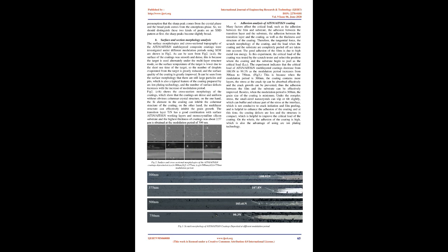The pitting of the AlTiN/AlTiSiN coating was carried out by an Anton Paar Tritech SA type pitting instrument, speed 500 rpm, time 600 s. The thickness of the coating can be obtained by observing the shape of the pits with a three-dimensional microscope. The hardness, H, and elastic modulus, E, of the AlTiN/AlTiSiN coatings were measured by the continuous stiffness method with a G300 nanoindentation instrument, and the H/E and H^3/E^2 values were calculated. The nanoindentation instrument is used to test the hardness of the prepared coatings with a load of 10 mN, taking an average of 10 values.